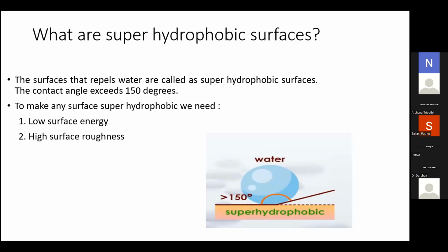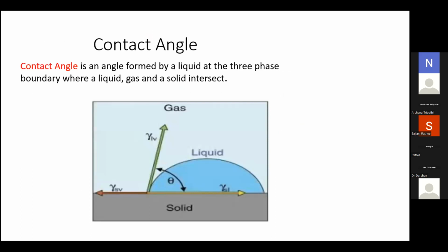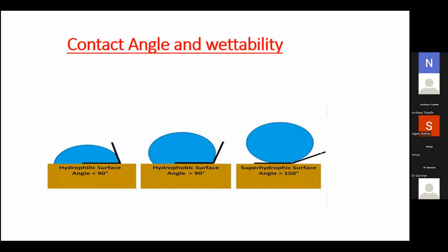And to make any surface super hydrophobic, we need low surface energy and high surface roughness. So contact angle is the angle which is formed here, where the gaseous phase, solid phase, and liquid phase intersect. This angle is called the contact angle. And if its value is greater than 150 degrees, it is called super hydrophobic.